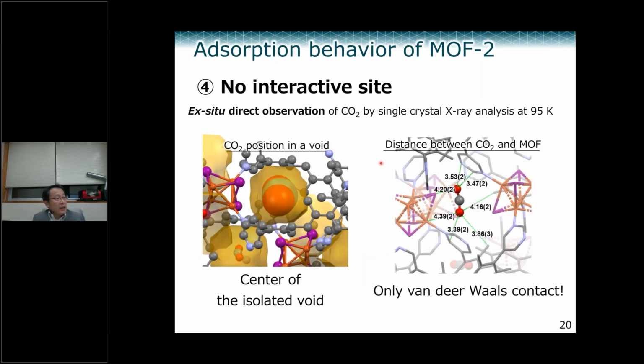Let me show the crystal structure in detail. CO₂ sits almost in the center of this isolated void. This figure shows the distance between the MOF and CO₂. As you can see, this distance indicates the interaction is only van der Waals contact. No strong chemical bond, no strong interaction between them. So this is typical of physisorption.